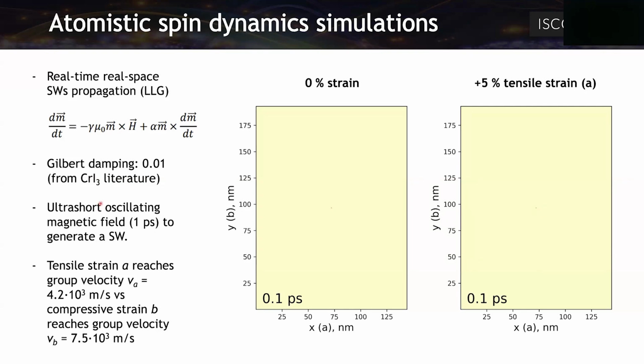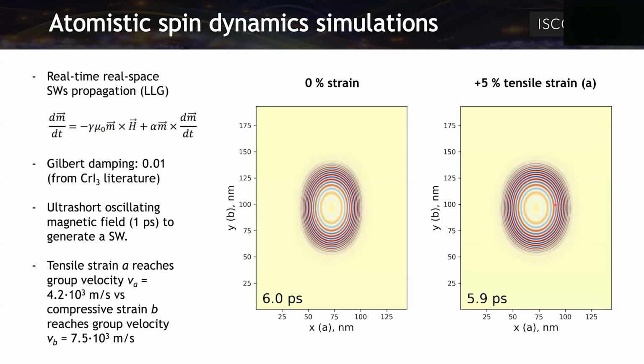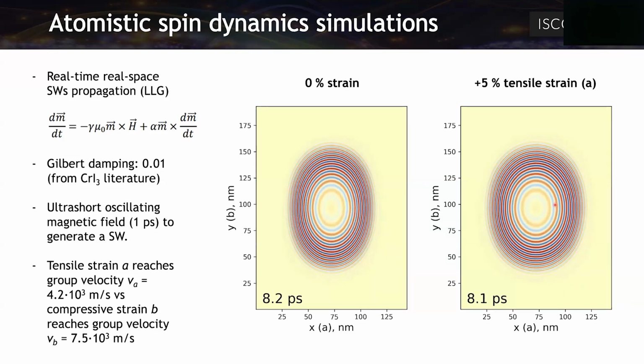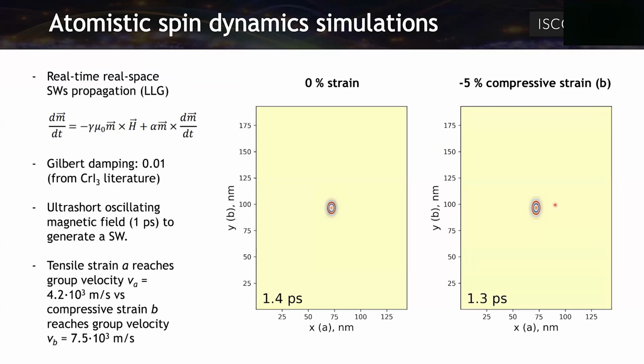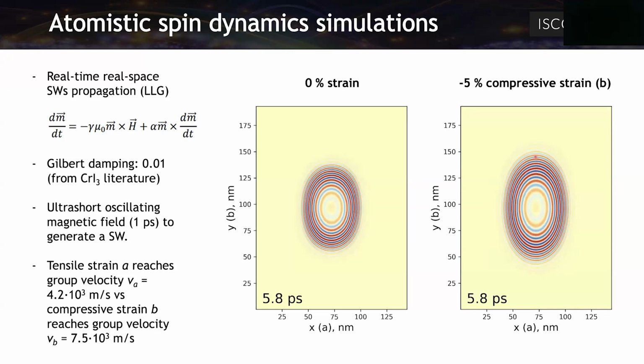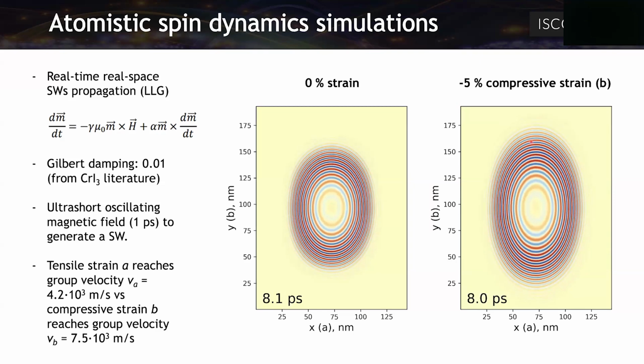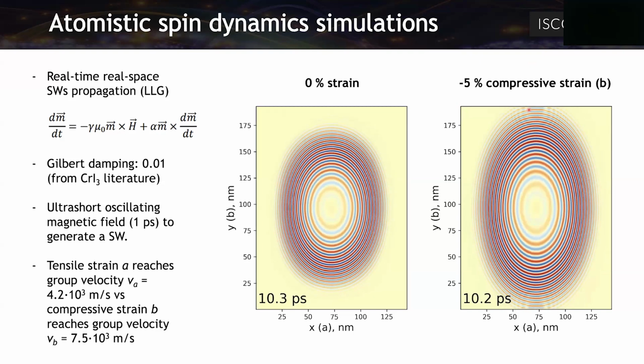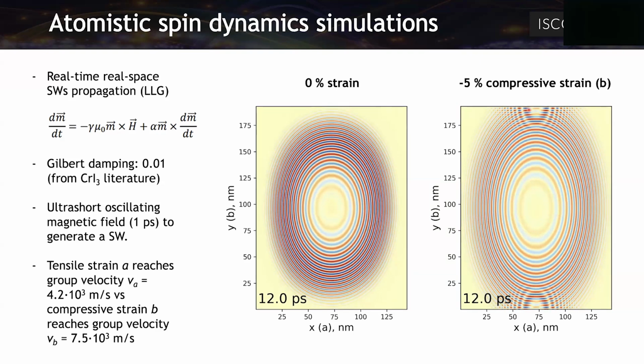And to create a spin wave, we provide an ultrashort oscillating magnetic field during 1 picosecond to generate a wave. So here we can see the effects for chromium sulfur bromide without any kind of strain and expanding along the A-axis. We can see here the simulation, and we will observe how the waves with this 5% strain are traveling faster along the X direction, that is along the A direction in the crystal. Then now we can check for the compressive strain. We are going to the case along B, and we can observe that the spin waves with this compression are traveling faster along the Y direction. So this reaches a group velocity of 7.5 kilometers per second according to this calculation. So the effect is that if we want to play with this compression along B, it will make the waves travel faster in this direction.